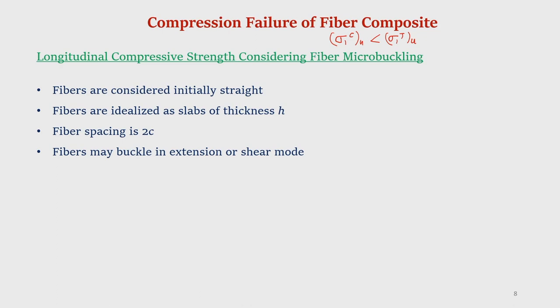There have been a lot of studies by many investigators, and Rosen has given an explanation in terms of understanding the compressive strength considering fiber microbuckling, and he has associated the longitudinal compression strength with the microbuckling of fibers, which leads to the failure. What has been considered is that